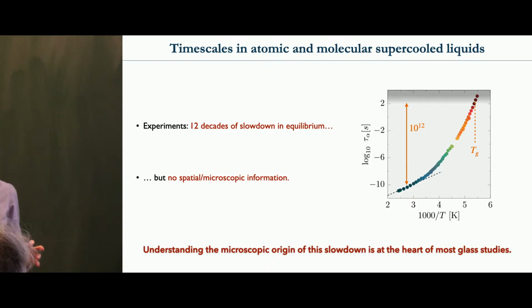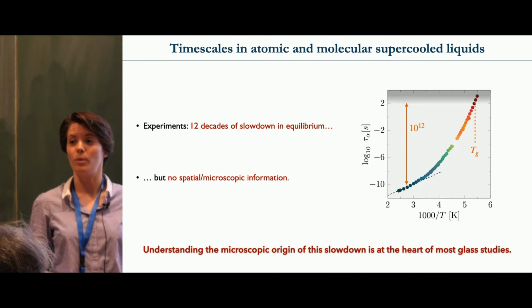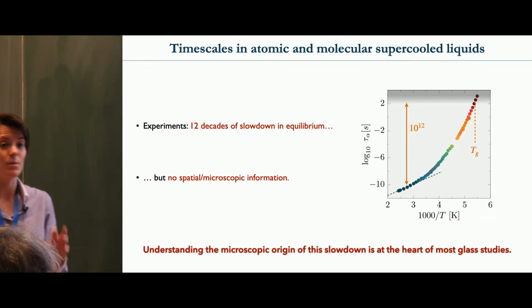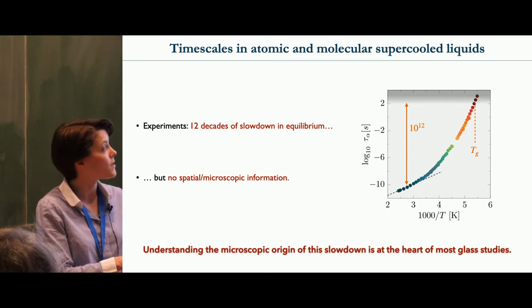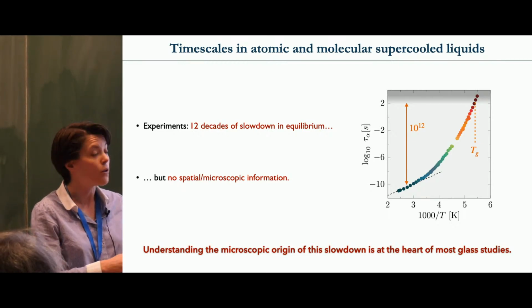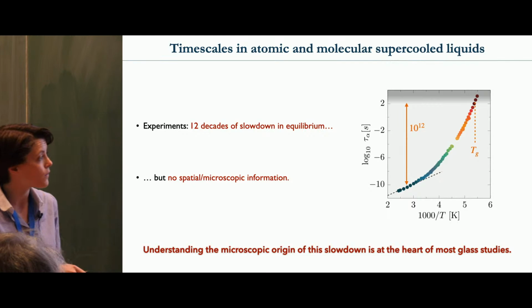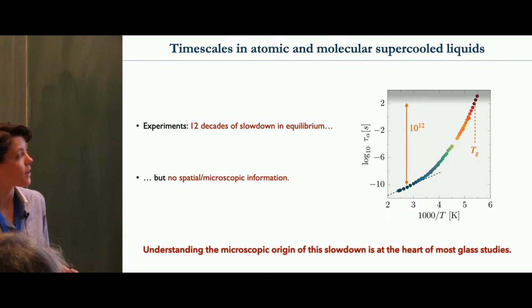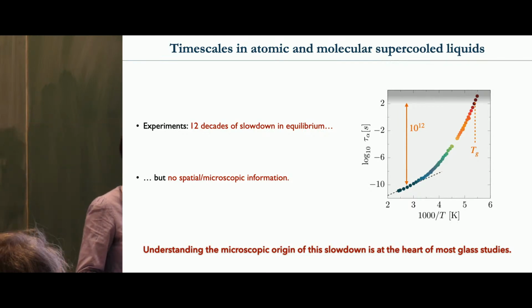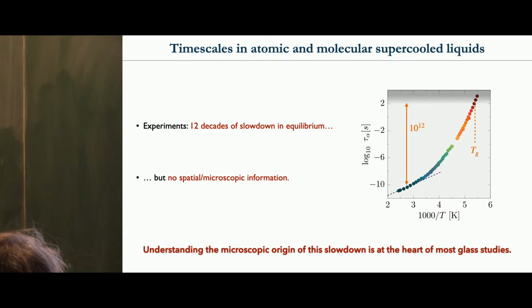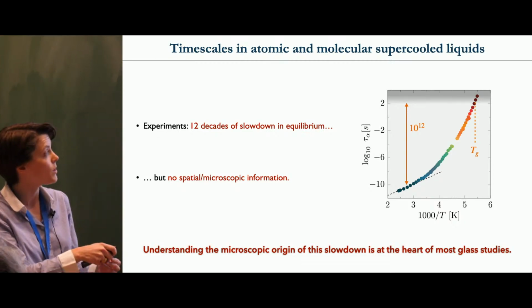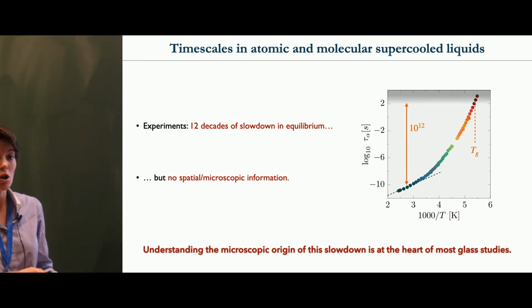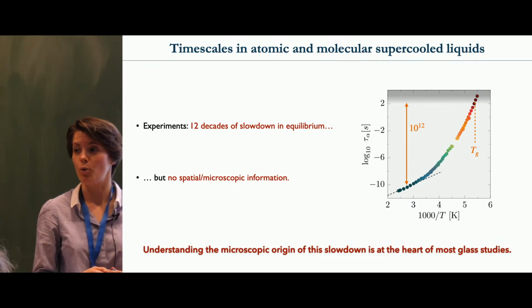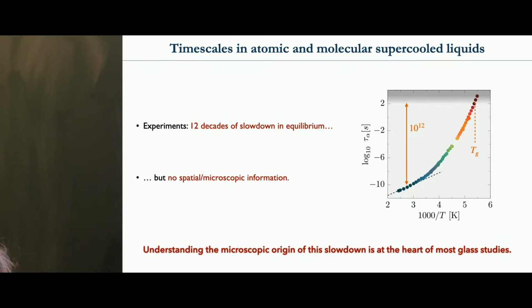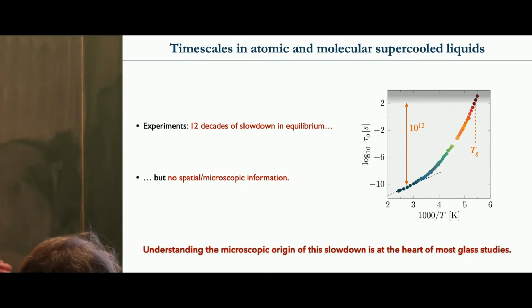So here I will be talking mostly about experiments on atomic and molecular glasses, which have quite specific timescales. So here in experiments, what you have is the relaxation time in logarithmic scale as a function of the inverse temperature. So low temperatures are on the right here. And what you can observe in many molecular or atomic liquids is this dramatic increase. And you have this huge slowdown by more than 12 decades. So you can observe these huge relaxation times.